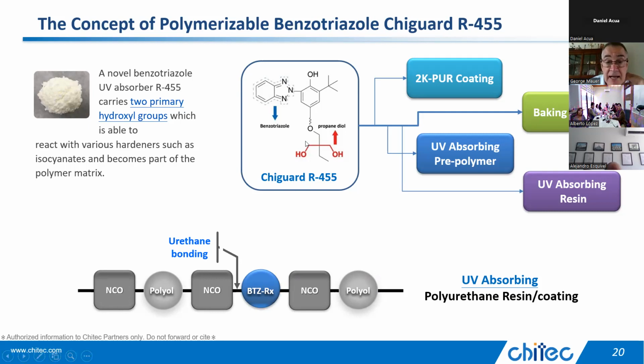And so it really reacts in very well. We've done a lot of tests to show that with a good NCO to OH ratio, essentially 100% of it is reacted in, most of it twice polymerized. And so it's really a great way to get a UV absorber into a coating that now can't migrate. It's part of your polymer system. It's built right in. So it's really an excellent way to try and beat Mother Nature.